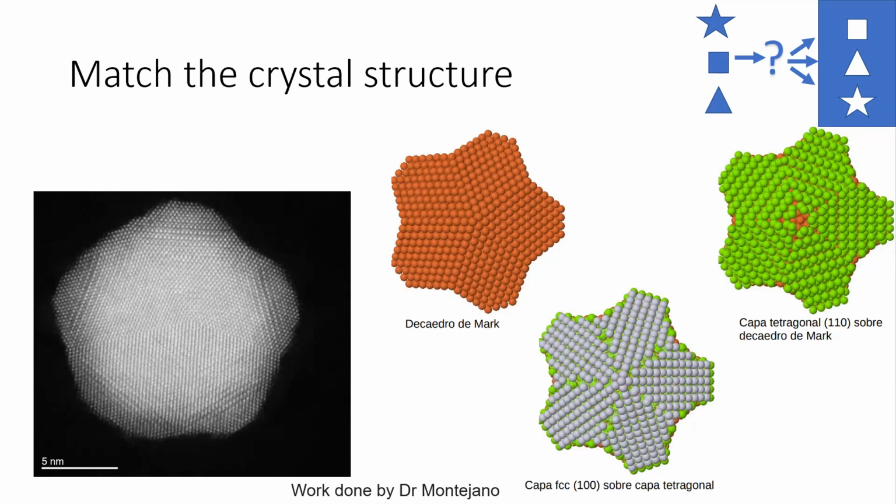With this particle, it's actually gold, platinum, copper. What we're seeing is that the gold and copper are alloying together and the platinum and copper are alloying together. So we're getting these different layers, where it's going to be the gold and copper of one, the platinum and copper of the other.